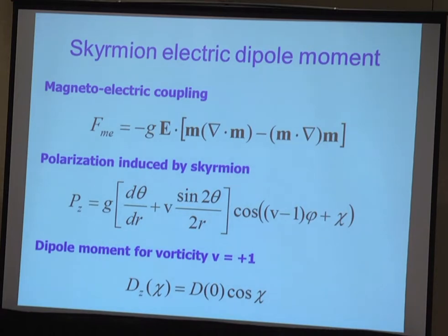Now let me discuss the coupling to electric field which is perpendicular to the plane. It's the same form as the coupling, but now I take the z component of the electric dipole induced by this inverse Dzyaloshinskii-Moriya mechanism.